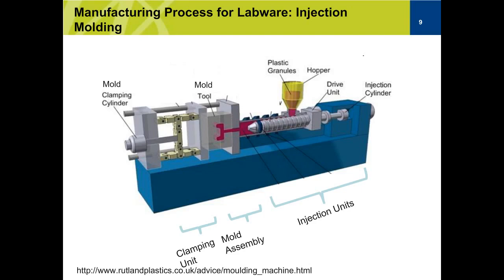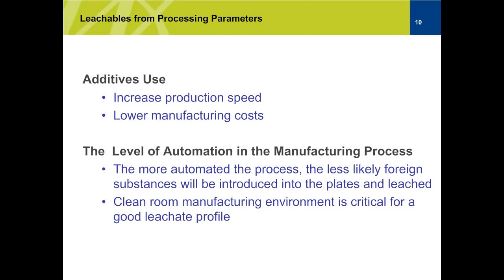But basically, in all injection molding, you have a hopper. That's where you put in your raw materials, and then after that, the cylinder gets heated. The plastic gets heated and gets injected into the mold, and then once the plastic takes the shape of the mold, the mold opens and releases the labware, and the cycle continues on and on. So this is an example of an injection molding process, and really there are a lot of additives that are added in here to make sure that the manufacturing process goes smoothly or increases the output.